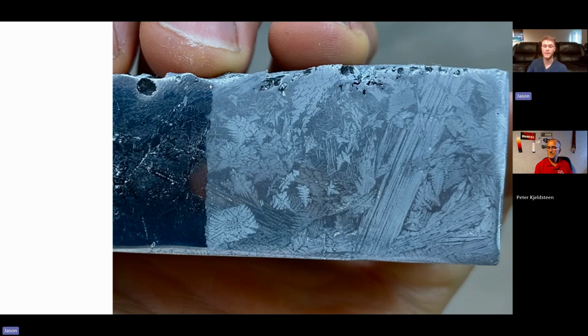And so this etching, complete tangent, but this etching actually took me quite a while to figure out. I think it's a really cool way to etch, because this material was incredibly difficult to etch. Usually you etch aluminum alloys with Keller's reagent, right? A mixture of hydrofluoric, nitric, and hydrochloric acid. Hydrofluoric is necessary to strip the oxide. Nitric passivates the aluminum, and hydrochloric selectively etches, pretty sure. I tried that etch on this alloy, and it didn't work very well. Didn't get very good phase contrast.